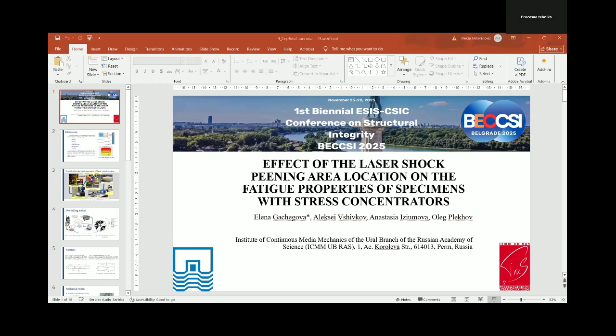During the early stage of loading, the crack did not grow, indicating that compressive residual stresses formed directly around the notch effectively reduce the local stress intensity. And the crack growth rate diagrams in figure 13 further confirm this effect.